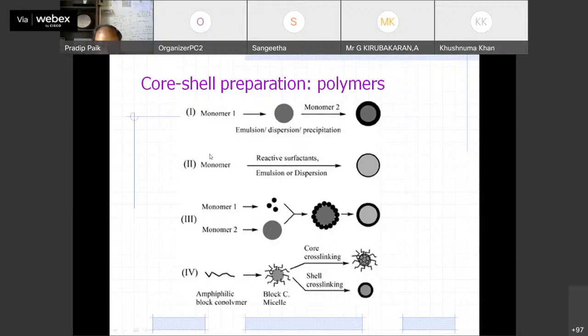Whenever you are preparing the core shell, let's say your aim was preparing the core shell, but you found that monomer 1 produced polymer 1 and monomer 2 produced polymer 2, so it's not making the core shell. It means that they are not compatible. Either one is hydrophobic and one is hydrophilic, or both have opposite properties. Ionic charge, if opposite, then they will be deposited. So ionic charge also can interact. If one is cationic and the other is cationic also, then deposit will not be there.